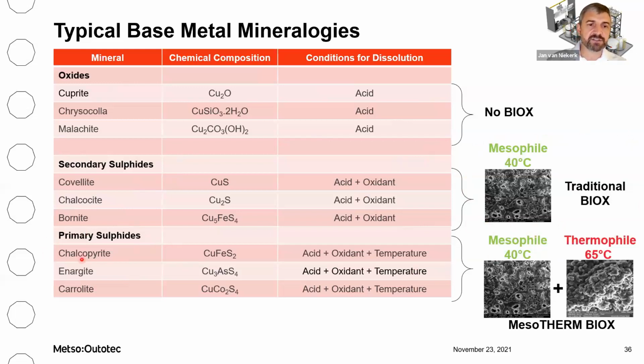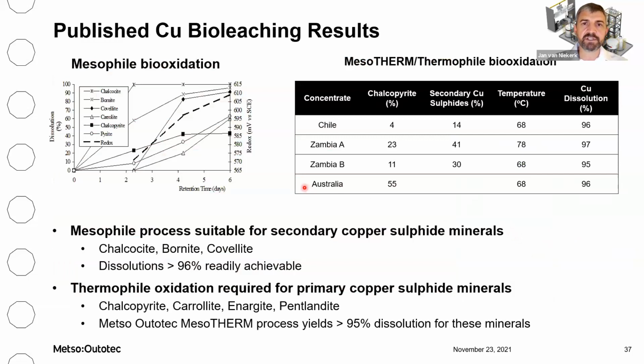But then for the primary sulphides, so chalcopyrite and enargite, you'll need the mesophile in combination with the thermophile or higher temperature bacteria. The reason for that is simply because the chalcopyrite mostly passivates under mesophile conditions at a lower temperature, and you'll only get a partial oxidation, and you really need a higher temperature to complete the oxidation. If you look at some published bioleaching results, this is for mesophile oxidation, and as you can see, for your secondary coppers you can get very high copper dissolution, but for your primary sulphide minerals the oxidations are much lower.